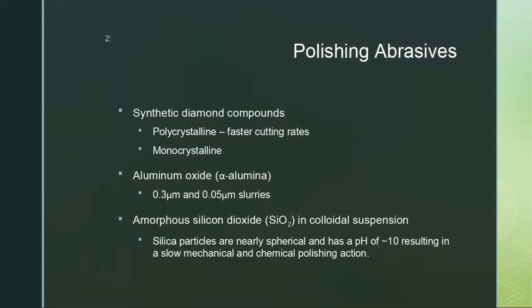And then the last one is your colloidal suspension. The silica particles, believe it or not, are spherical, nearly spherical, with a pH of about 10. This process is very slow in terms of mechanical and chemical polishing. So if you're using a colloidal suspension, chances are you have a greater chance of rounding out your edges. I never go to this length. I believe your aluminum oxides and colloidal suspensions are best used in the vibratory polisher more so than in mechanical, manual, or automated polishing steps.